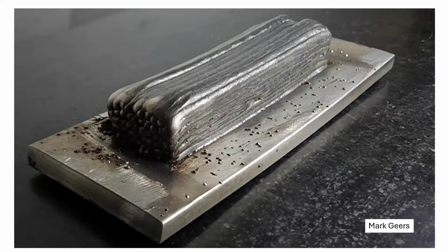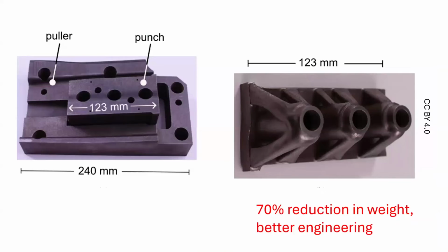So just to show you another set of problems, this is by depositing layers. And you can see here that this plate, which was originally flat, is no longer flat because you've got liquid contracting, etc. So you will have large residual stresses in there. Whether that matters or not, I don't know. The surface here is also not smooth. So you will have to do some other operations afterwards. But this is an example which cannot be done without additive manufacturing, and it saves 70% steel. So this is a tool used in industry, and you make it by machining.